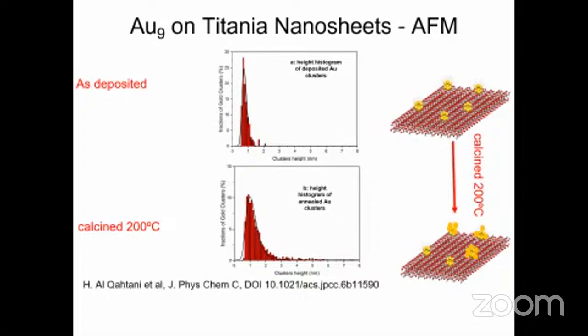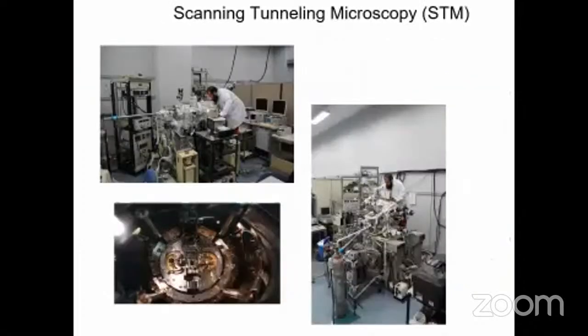We also use a scanning tunneling microscope. It's not an easy technique to use, and it's a bit challenging because you are getting the tip itself very close to the sample, just on a gap of 1 nanometer. With any contamination, any impurities, any kind of damage, you will lose the signal.